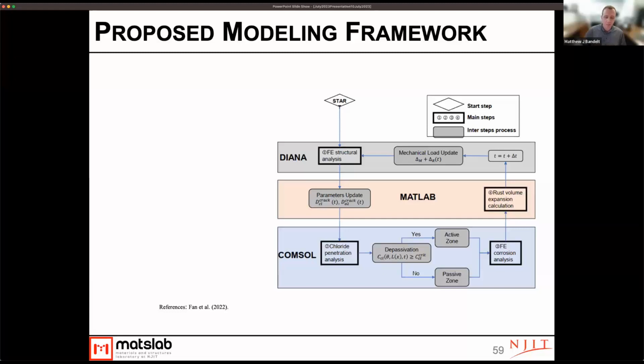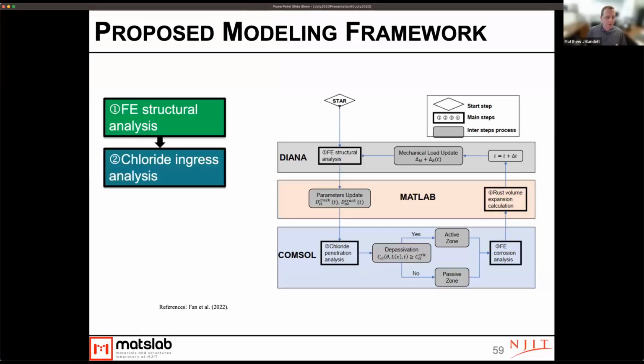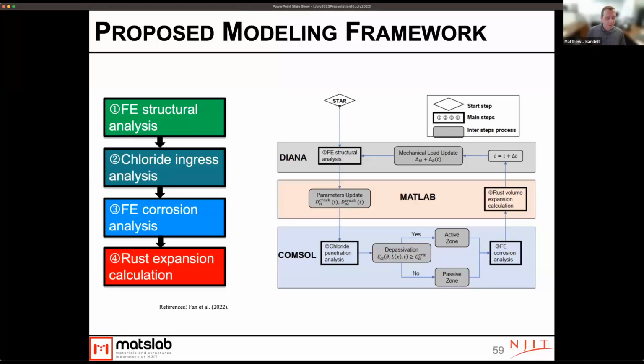And so what we were able to do was basically link these pieces of software and simulate a fully time-dependent behavior from sort of initial structural mechanics to chloride penetration to corrosion analysis, which causes expansion, and then additional cracking, et cetera. And we were able to look at the time-dependent behavior of different samples. And so these were the main steps: structural analysis, chloride ingress analysis, corrosion analysis, and then simulating the rust expansion calculation and repeating this over time.